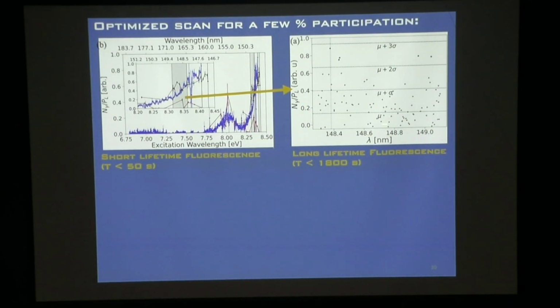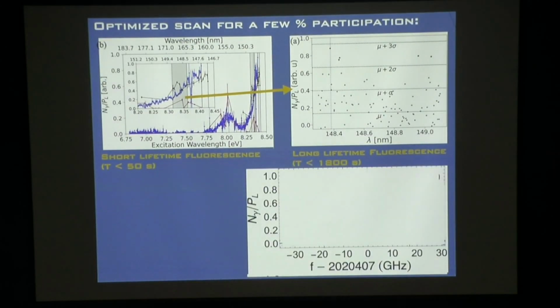And you see there are about 5 points here that were more than 2 sigma fluctuation from the mean, not that surprising over 100 points. But there was one point, the highest point here, that was almost 3 sigma. And so when we went back to that point, what we saw was a tiny little bump that was about 10 gigahertz wide, which is the width of our laser. And so we saw a little signal there. We've never seen anything like this anywhere else.